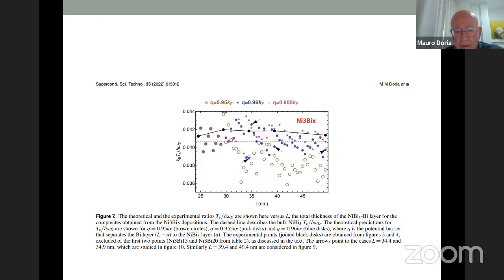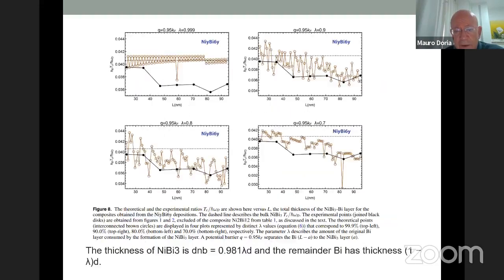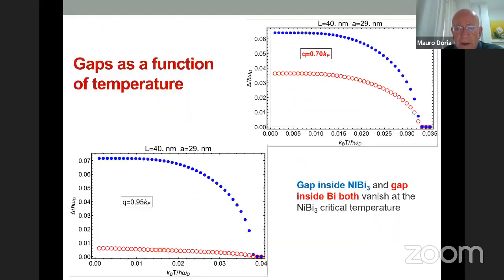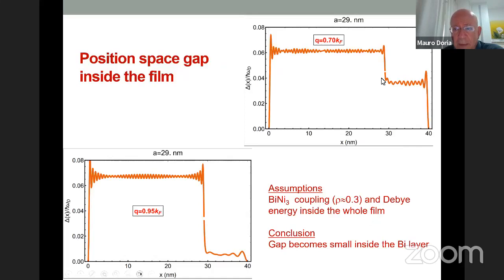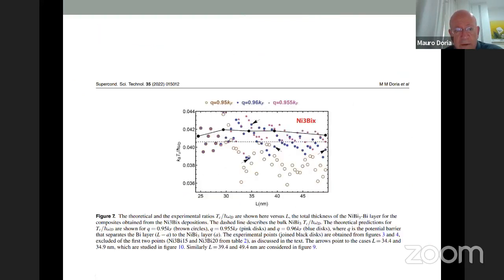But these are our two final plots, figure 7 and figure 8 of the paper, which support the assumption that these resonances may exist. But most important, we are able to explain why. The basic idea is that the gap percolates into the bismuth and exists here. This is what influences the critical temperature according to this thickness. Because in principle, only this part is superconducting, and this is not. But we claim that this thickness also influences the system. So I think this is all I have to say.